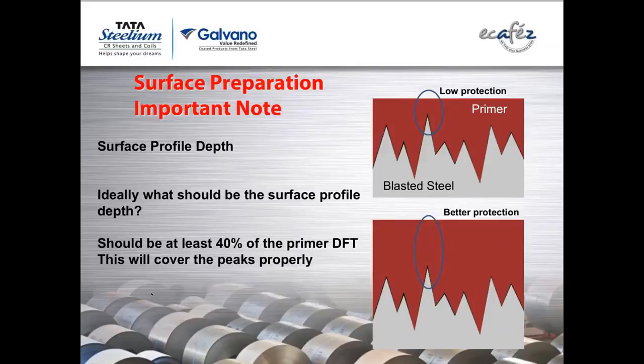On a plain white panel you might have seen small pinpoint rust; that usually happens because of this. In the second picture, there is enough thickness of primer, so the protection will definitely be better. So a thumb rule is it should be at least 40% of your primer DFT. If the profile is more and you cannot control it, then you need to increase your primer DFT. In short, the more the surface profile, the more your primer consumption is going to increase. So basically, try to have a look into this.